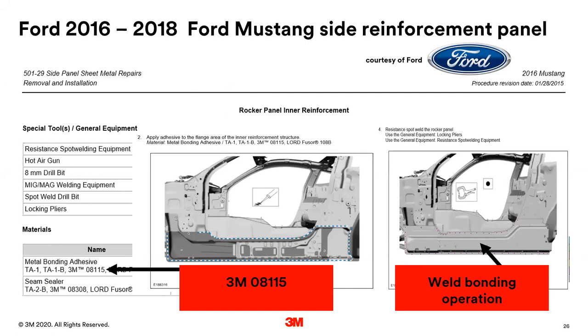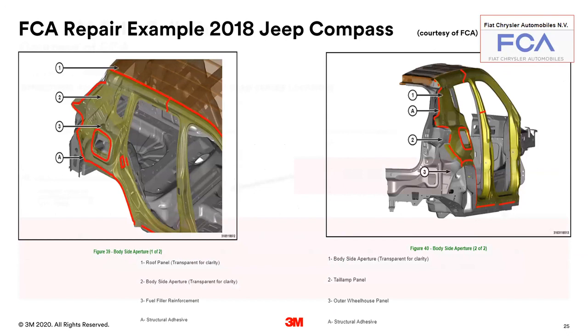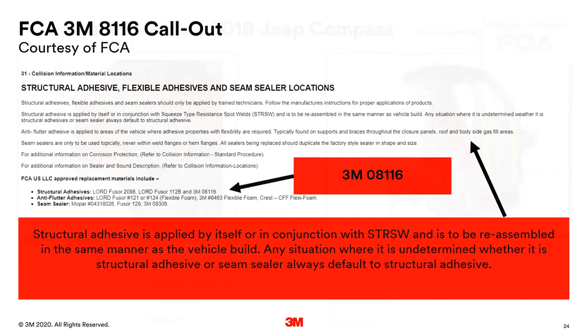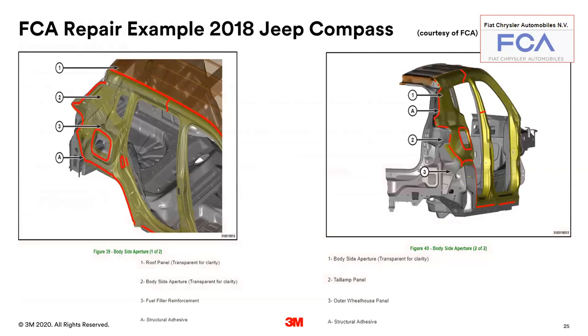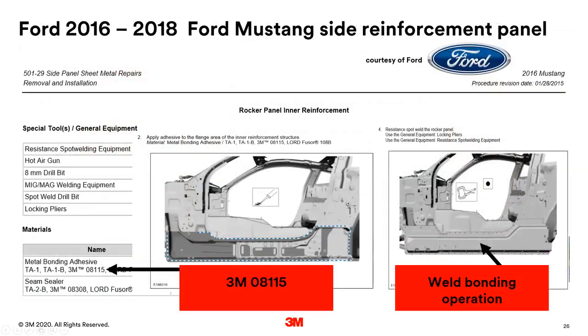I do want to give you one other caution, by the way. I'm going to back up one screen, 2 screens actually, because sometimes some of these manufacturers are still calling panel bonding adhesives, they're using the terminology structural adhesives. So there's a difference between a structural adhesive, which could be a panel bonding adhesive, and an impact resistant or crash toughened structural adhesive. So when you see structural adhesive, usually they're talking about an impact resistant structural adhesive, but always check it out, because a couple companies I see, Ford and Fiat Chrysler are still calling it a structural adhesive when it's a panel bonding adhesive. So be careful about that.